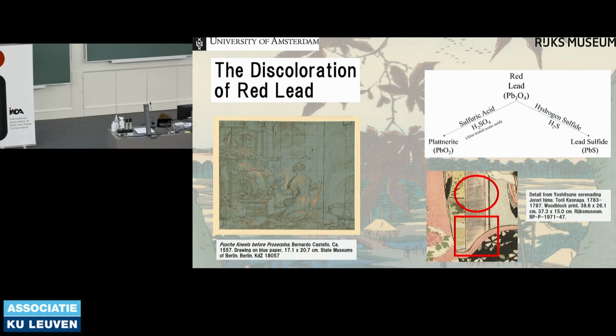The reason for this discoloration is particularly interesting on Japanese prints for two reasons. Number one, particular patterns are observed in the discoloration, and number two, there's some suspicion that some amount of this discoloration may be intentionally applied onto prints. So the patterns observed are these: either lines streaking across the print like this, or a sort of haloing effect, where around the edges of the printed area, there's this section of undiscolored pigment along the edges. The reasons for these patterns as of right now are completely unknown.